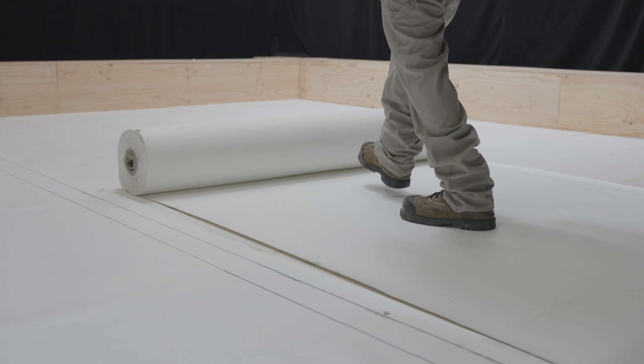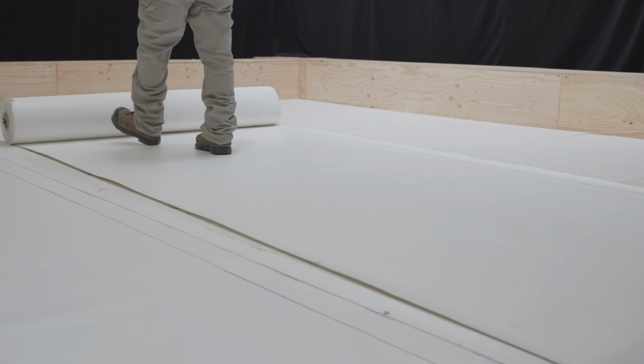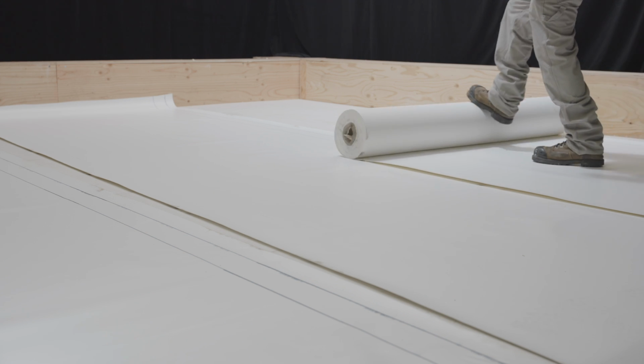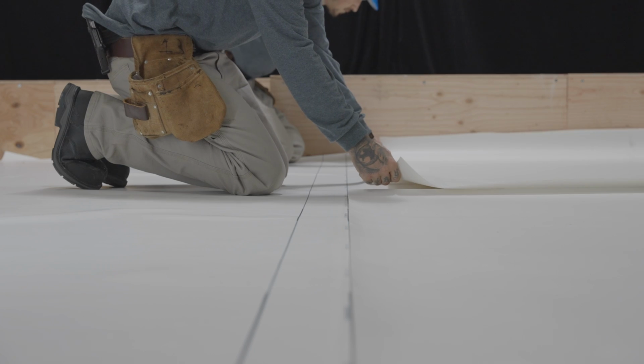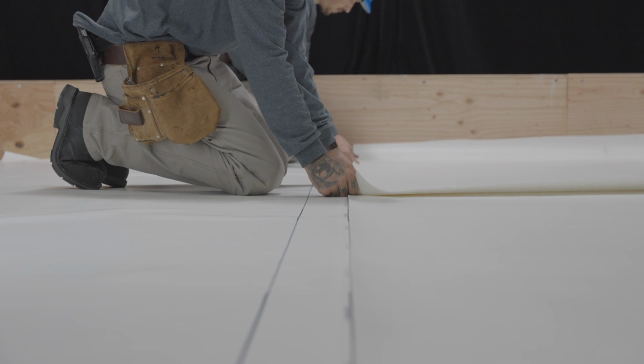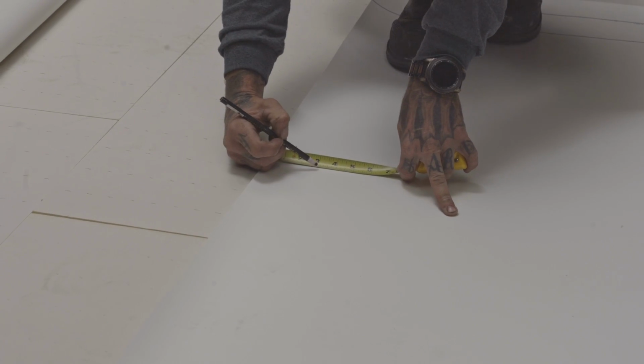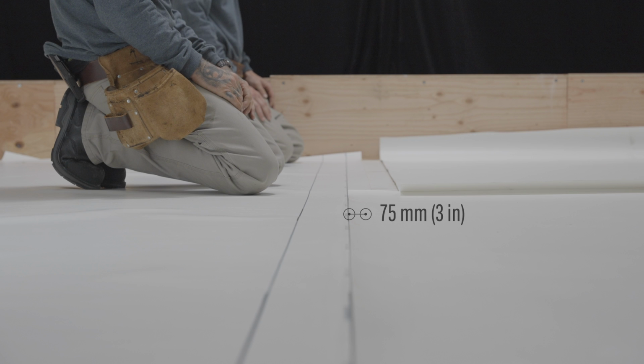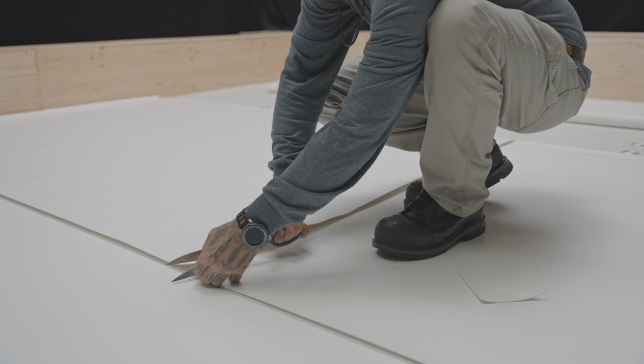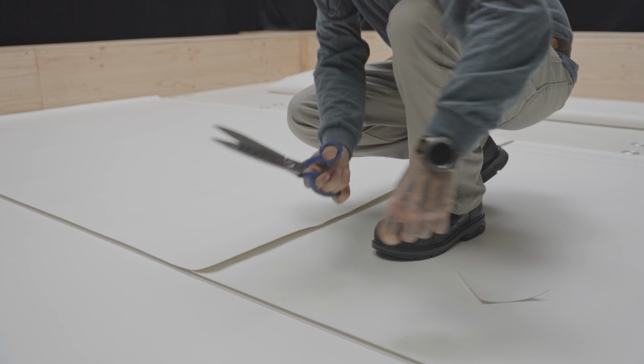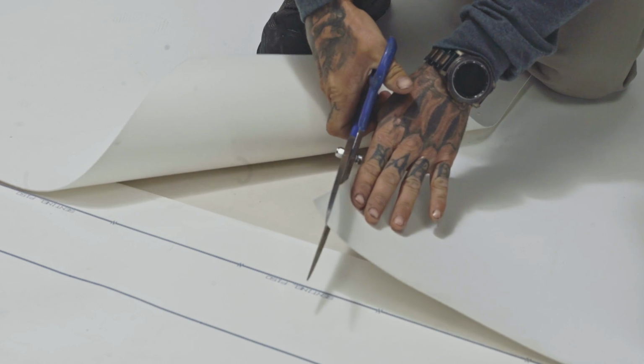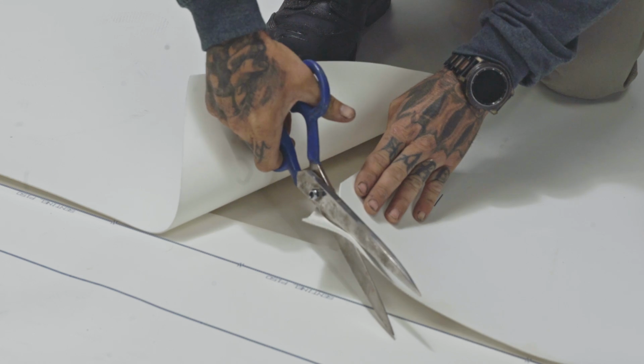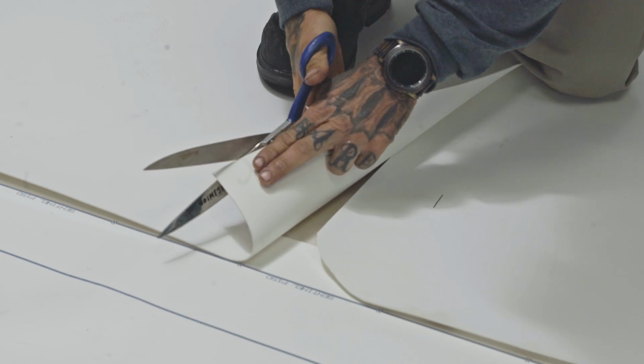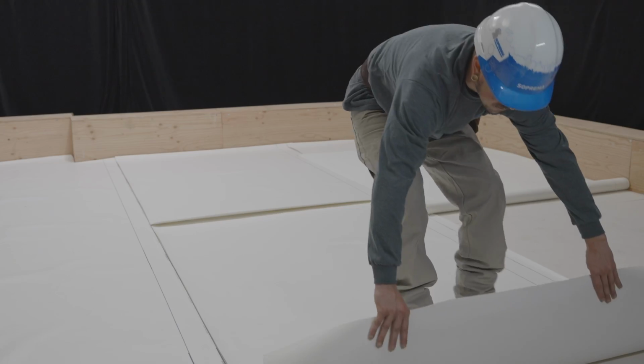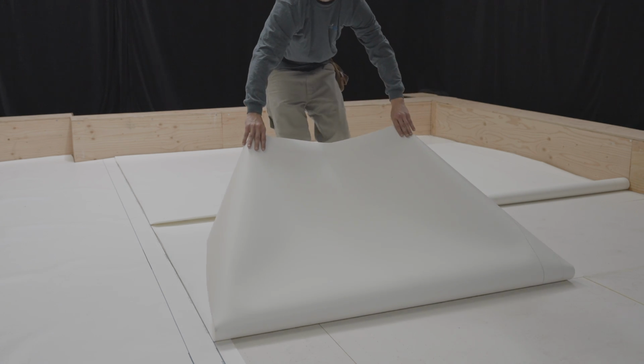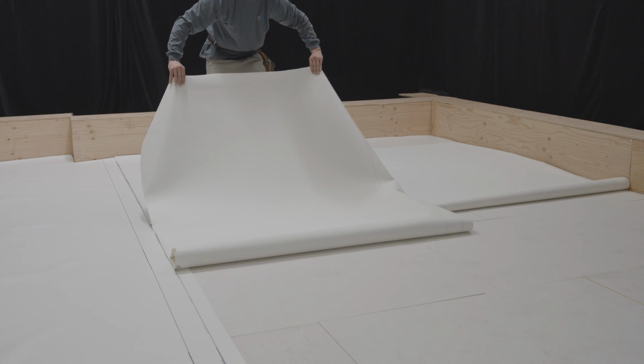Unroll the membrane in place on the substrate in order to dissipate the tensions accumulated during manufacturing and to facilitate its installation. In order to properly position the membranes, you must take into consideration that the sides and end laps must be at least 75 millimeters. The corners of the end laps must be cut to limit over thicknesses. The membrane below the overlap should be cut at an angle, while the corner of the membrane above the overlap should be slightly rounded. Now that the membranes are in place, fold them back on themselves in preparation for applying the adhesive.